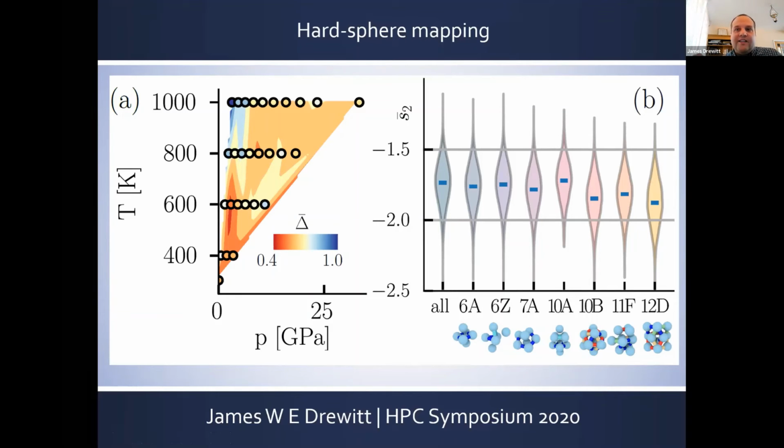So as indicated in our structural measurements, the liquid does indeed tend towards resembling a hard sphere structure at high pressures and temperatures towards the melting curve here. But there remains a large deviation of greater than 40% from this simple description over all pressure and temperature conditions.